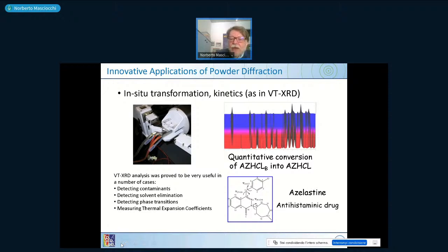This is a quantitative conversion of a butanol solvate of azelastine, which is the drug you see down there, into the hydrochloride where butanol is lost. So basically, you can detect the solvent loss. You can also detect the presence of contaminants, because one contaminant can melt before the other, the main material. So some peaks will soon disappear, or the contaminant is melting at higher temperature, so your peaks are disappearing before those of the contaminants. So this can also be a way to have a qualitative analysis of your solid material.